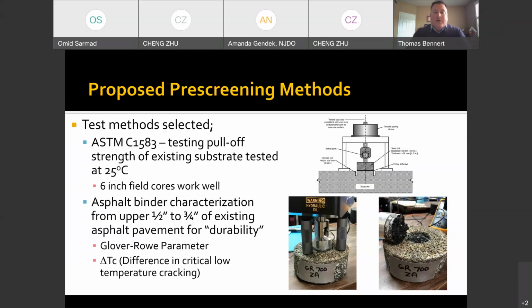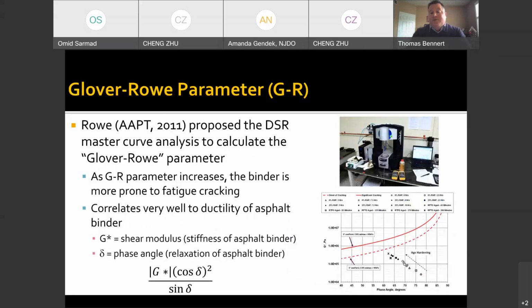And there's two different asphalt test methods that we can utilize. One's called a Glover-Rowe parameter, delta T sub C from a bending beam rheometer. And these are fairly simple and routine to run in the laboratory. The nice thing about this particular parameter, the Glover-Rowe parameter, is you can get all the material that you need from really one core if it came down to it. You only need approximately 5 to 10 grams of material to run duplicate, triplicate samples. And it provides you with an idea of the relative stiffness aging of the material. And there's some thresholds that have been developed to determine whether or not the asphalt binder is good.